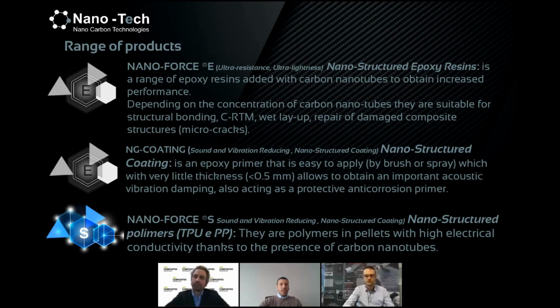At Nanotech, we started formulating Nano-Force E epoxy resin. That is a nanostructured epoxy resin, nanostructured with multi-walled carbon nanotubes. The resin is suitable for a lot of different processes, like bonding, wet layup, repairing of damaged composite structure, and has also been used for compression RTM.